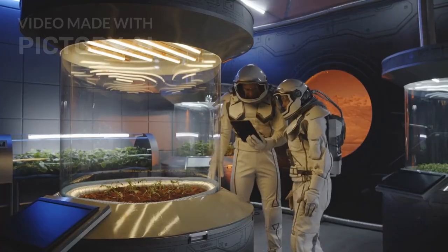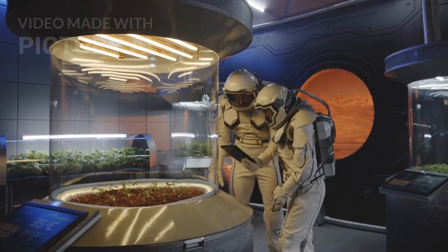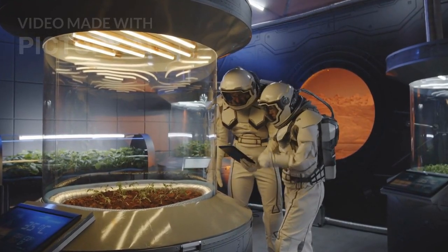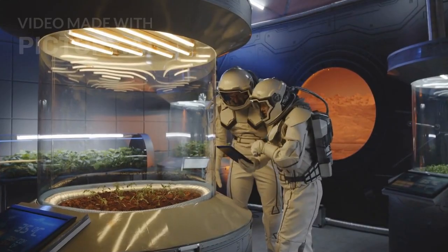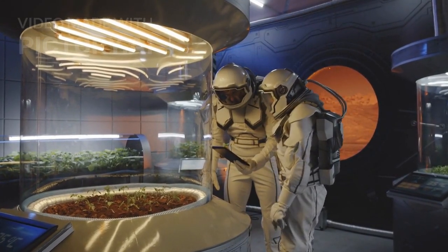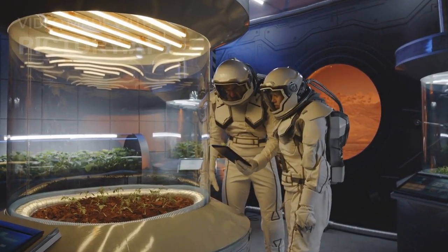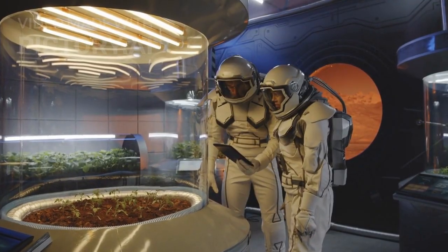92. Okay, let's get some context here. How does that compare to regular concrete? Or those other ideas? Right, so high-strength concrete, the stuff we use on Earth for demanding applications, is typically defined as over 42 MPa. Okay. So StarCrete, especially that lunar version at over 90 MPa, is easily in the high-strength concrete range, maybe even beyond typical high strength.